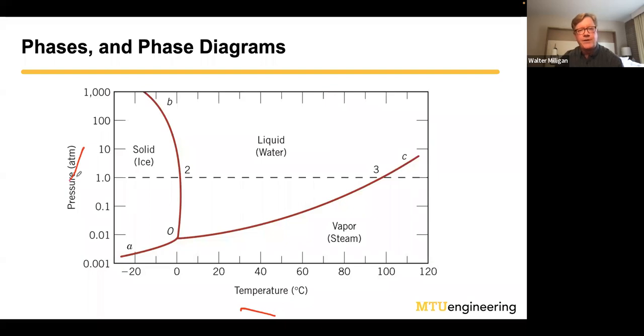And at its simplest, the phase diagram tells you what phases are stable at the combination of variables in question. So for example, at 1 atmosphere pressure, which is just regular room temperature conditions, and at 20 degrees C or so, which is room temperature, you would come up and plot that point there, and you would be able to read that the stable phase is liquid at that combination of temperature and pressure. If you keep the pressure the same and change the temperature, you can see where water boils, it's 100 degrees C. You can see where it freezes, it's 0 degrees C, for example. And you can also change the pressure and figure out what phases are stable.